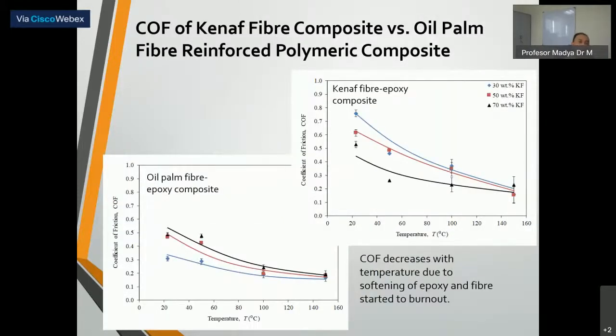This is the result of the friction of the kenaf and also the oil palm fiber. The trend is similar, where the coefficient of friction decreases with temperature. This is actually due to the softening of the epoxy, and also the fiber started to burn out. We can see that by increasing the fiber content, the friction coefficient is lower. But for the oil palm fiber it is vice versa: by increasing the fiber, the coefficient of friction is increased.